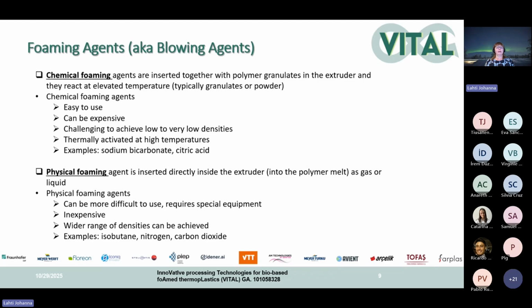Then physical foaming agent is typically inserted directly inside the extruder into the polymer melt as a gas or as a liquid. These physical foaming agents can sometimes be a little bit difficult to use. They require special equipment, for example, if we are using gases. But as mentioned, they are cheaper to use than chemical foaming agents. And with these physical agents, we can achieve wider range of densities compared to chemical foaming. And some examples, once again, for example, isobutane, nitrogen, or carbon dioxide.